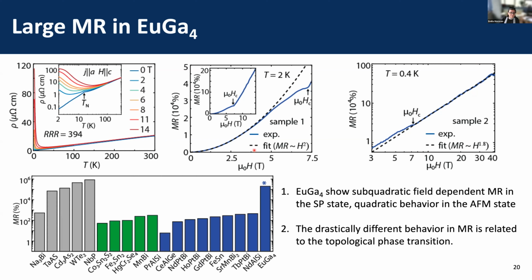And when compared with all the other large magnetoresistance compounds, which can be classified in 3 categories: paramagnetic, ferromagnetic, and antiferromagnetic, notice that the largest magnetoresistance seems to prevail in paramagnetic systems, with 1 or 2 orders of magnitude lower magnetoresistance in most magnetic topological systems.